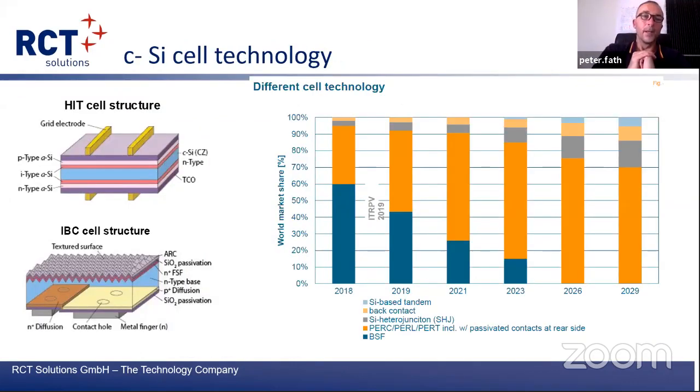Next, please. So here, as the previous speaker said already, we also want to show some new trends after PERC, what is coming next. We have the so-called heterojunction. You're not using diffusion, you're not using some type of thermal processes. You are just making coatings. You are choosing a very good wafer. You have to use a so-called N-type wafer. That means we are not using boron, we are using phosphorus inside the silicon lattice for the wafer. And then we are doing just some coating, intrinsic amorphous silicon or doped silicon. So we are coating silicon on silicon. And then we have to make the antireflective coating and the same metal contact as I explained for PERC. And then you can make a heterojunction cell structure. Typically, the efficiencies are about 1% absolute above the PERC cell. So that is an advantage if you go to heterojunction.